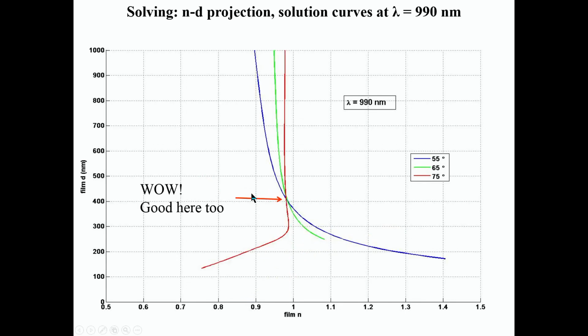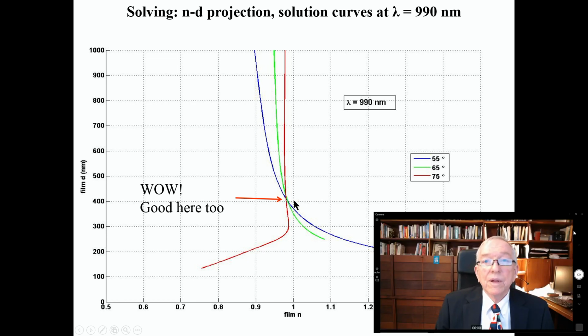Well, before that, I also want to look at it in the thickness plane. I don't usually do this, but just to see, is this realistic? Are they coming to the same thickness when they do that sharp intersection? And the answer is yeah, they are. So we've got something that we can work with here. A real live intersection with good mathematical condition. And P.S. by the way, we only have to solve for these thicknesses at one wavelength. They're going to be the same at all the wavelengths. So we could take this information and apply it to the other wavelengths, a very handy thing.